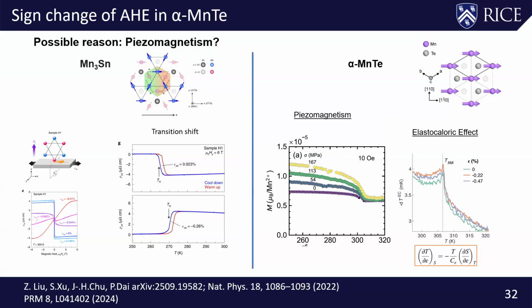Uniaxial strain changing the anomalous Hall effect in terms of a sign change has been seen before. For example, it has been seen in manganese tin and a few other systems. So when you put a uniaxial strain, you can change the anomalous Hall. But in this situation, the system is quite different. In the case, for example, of manganese tin, your magnetic structure is non-collinear, and not only is it non-collinear, it's non-coplanar. That basically means that when you put a uniaxial strain, you can induce a very small, non-zero scalar spin chirality. And therefore, your anomalous Hall effect is basically what we typically call a piezomagnetism effect.